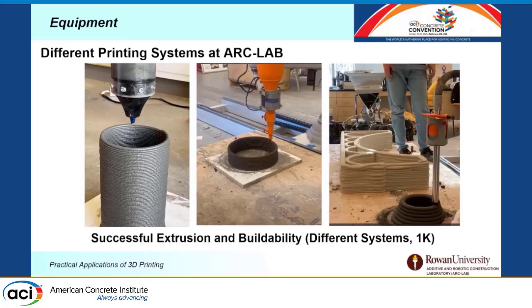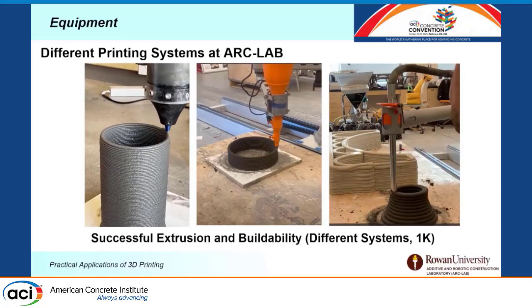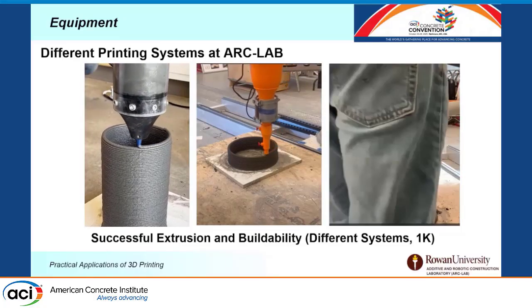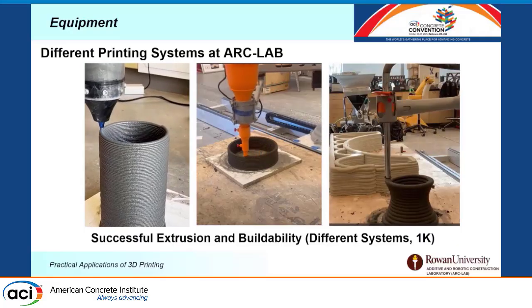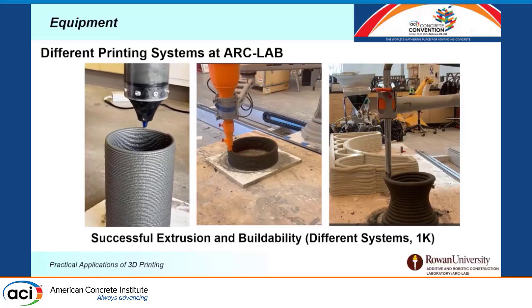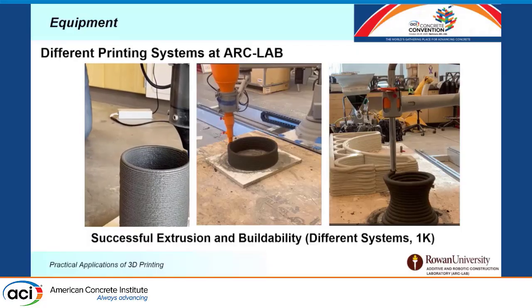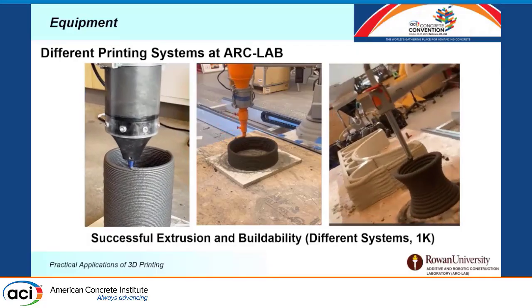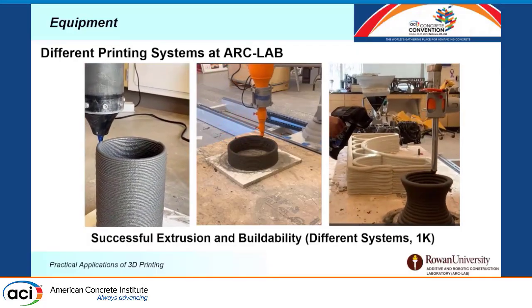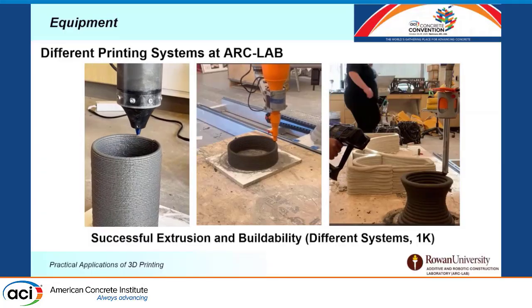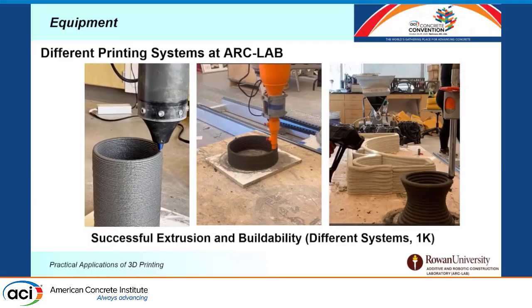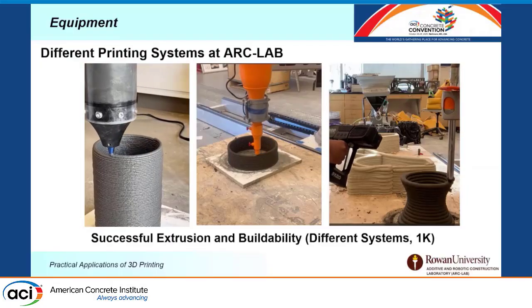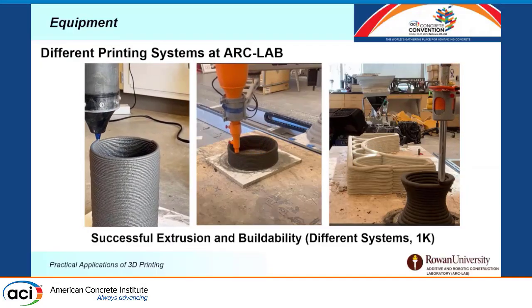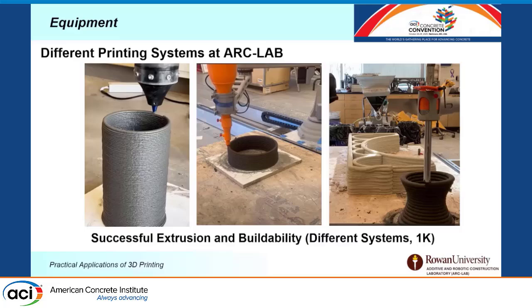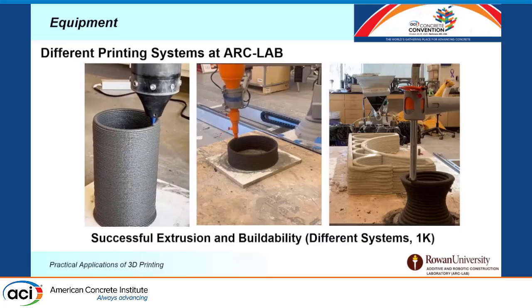So to show here are our 3 systems that we have side by side, starting with a smaller tube to extrude material, then an open auger, to feed the material to the auger and extrude, and also the open system where you have the pump extrude the material just to the end of the hose nozzle. And the same material is actually printed from all 3 systems with a little bit of tweaks on the rheology.